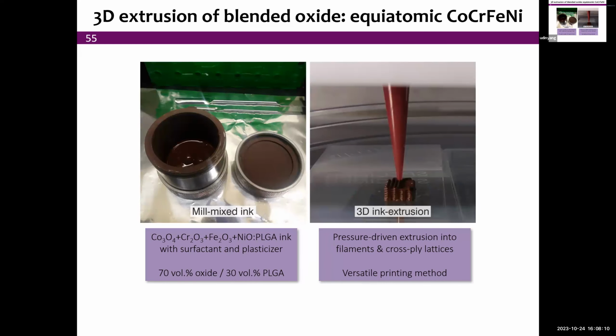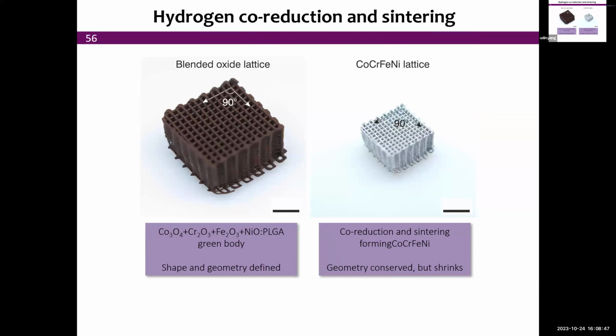Okay, so now we'd like to go to so-called high entropy alloys, or multi-principal alloys, where we have at least 4 elements that are all at the same amount, equiatomic, as we call them. So this would be cobalt, chromium, iron, nickel, each of those elements being 25%. We've done iron, nickel, and a little bit of cobalt already. So chromium would be the next one. We do a mixture again of cobalt oxide, chromium oxide, iron oxide, nickel oxide. We extrude 3D print, as shown before, the blended oxide lattice. And after co-reduction and sintering, we have, again, a very nicely conserved geometry, but a highly shrunk microstructure or architecture of the material. So that works.